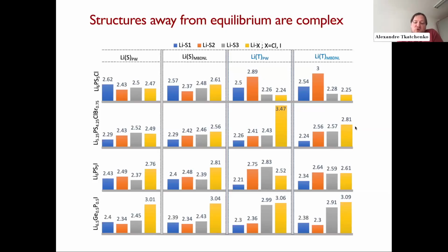It's a huge change in the geometry, which agrees with our old work on diffusion of defects in silicon, where we also observed quite significant differences in the geometry upon including van der Waals interactions. We see the same here. So basically, softer frameworks, which is exactly what happens here for this mixed anionic framework, can lead to very large changes in the distance due to the inclusion of many-body dispersion effects. That's quite surprising, but that explains why there are such large differences in the transition paths.